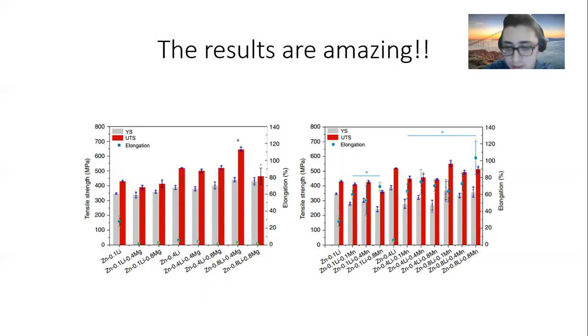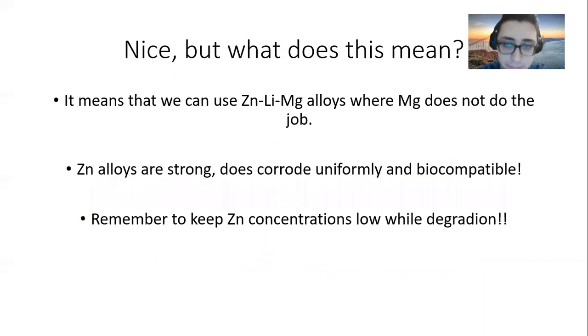And on the right are the manganese alloys. Now, their ultimate tensile strength is quite impressive again. But what's really impressive about these manganese alloys is their elongation. They elongate almost up to 80%. Not on average, but for a good alloy. They elongate up to 80% before failure, and that's a really, really good number.